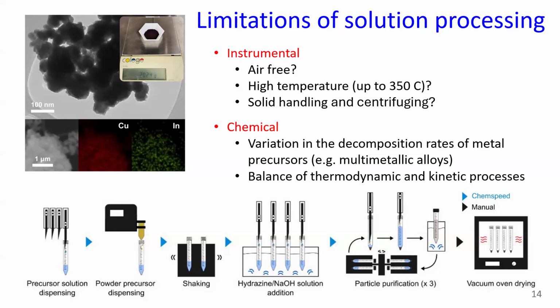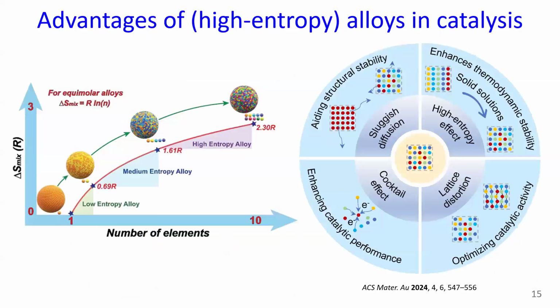solution phase synthesis, such as it's particularly difficult to make multi-metallic alloys and high-entropy alloys with colloidal chemistry, because oftentimes there's a variation in the decomposition rates of metal precursors, which makes achieving multi-metallic alloys and specifically high-entropy alloys challenging.